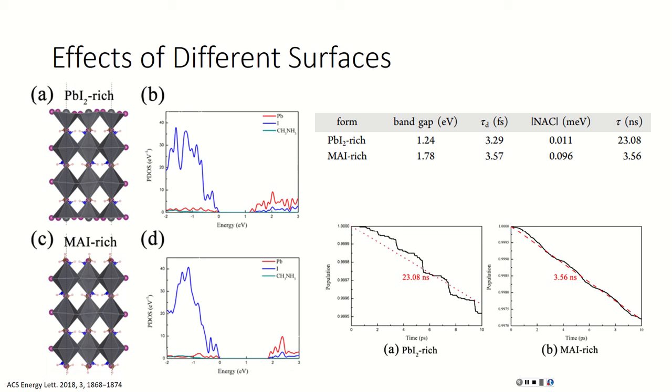You can see that they're relatively the same in time, so that's not too much of a difference maker right there. A couple of femtoseconds isn't too much of a difference. One of the bigger differences we see is the last two things. Non-adiabatic coupling is what the NAC stands for. So that really crude explanation I gave for it is where that's coming from. And tau is the excited population, how long until they relax down to the ground state.